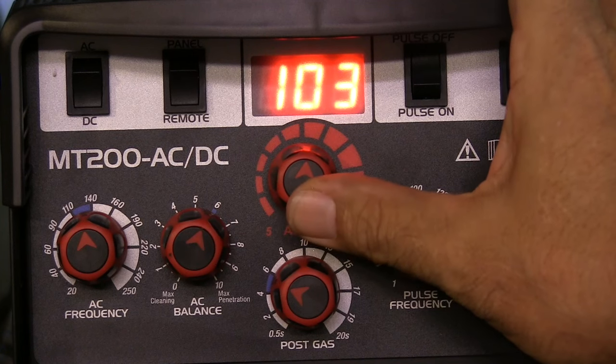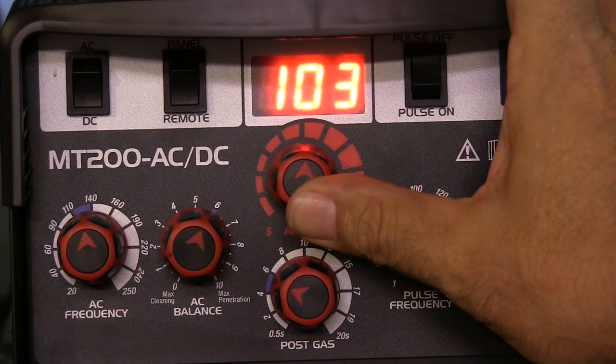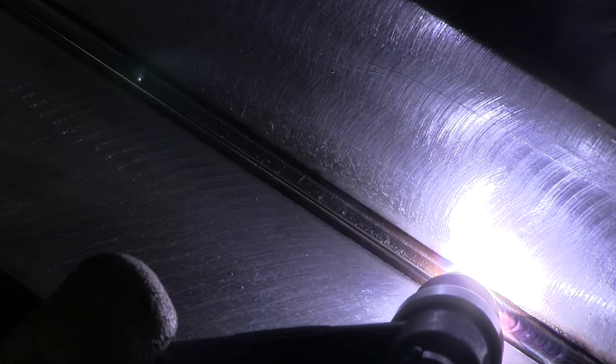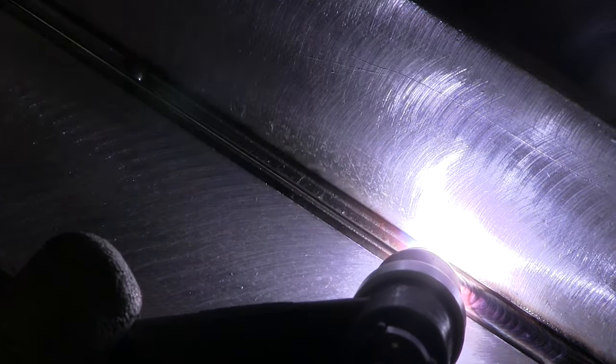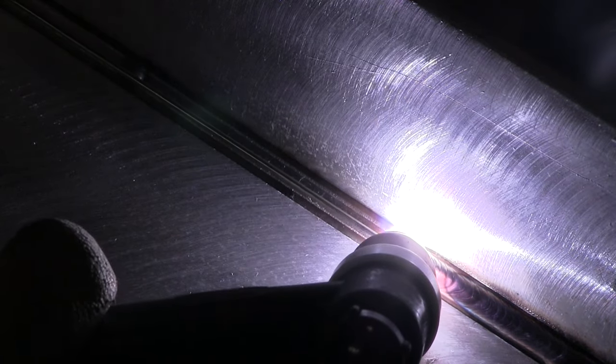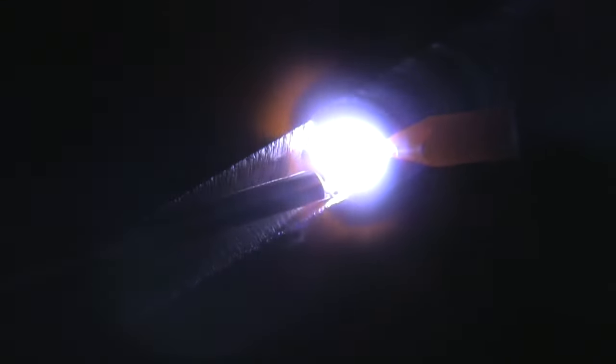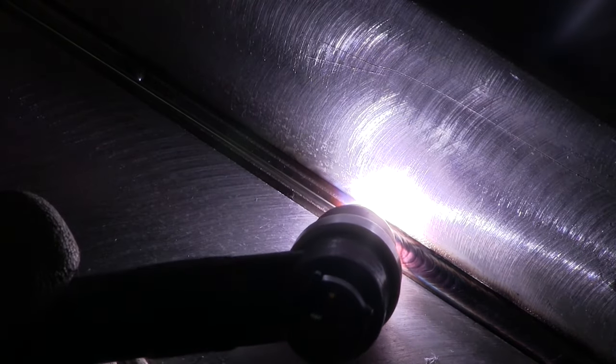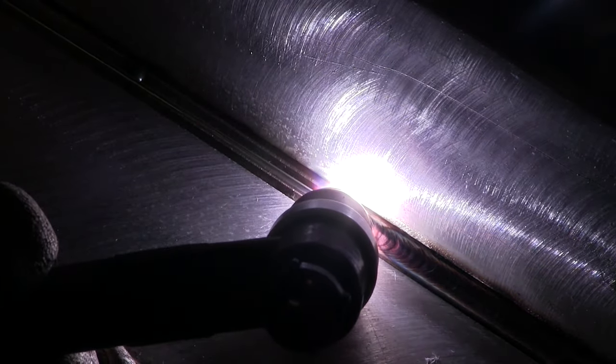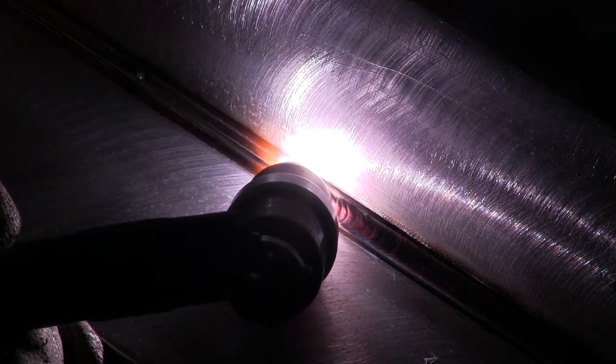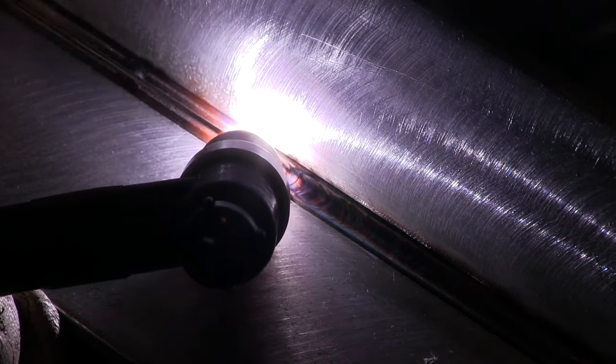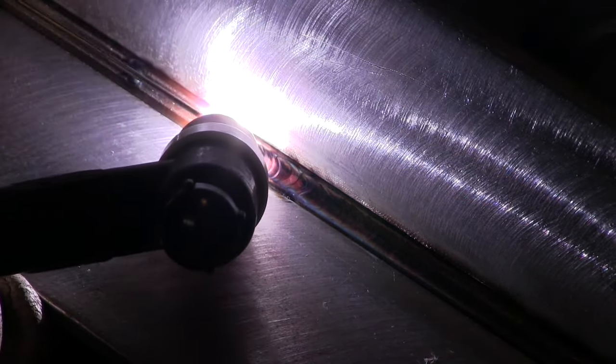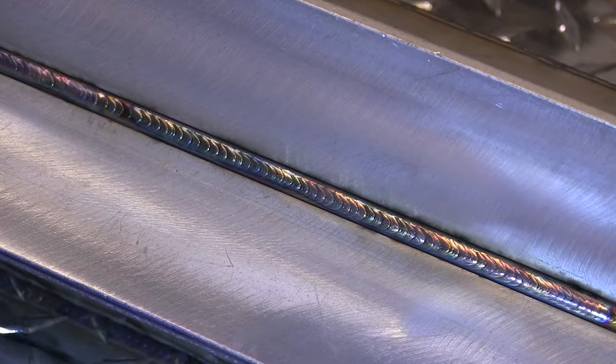I used them on the outside and made a little trough with some heat sinks. Clamped everything down good and tight. Here I'm just using a standard number eight gas lens cup moving along at a fairly good clip at about 100 amps. To get this level of shielding, I would need a much larger cup without these chill bars. Chill bars are really good for stainless and pulling the heat out. That's always good to prevent warping.